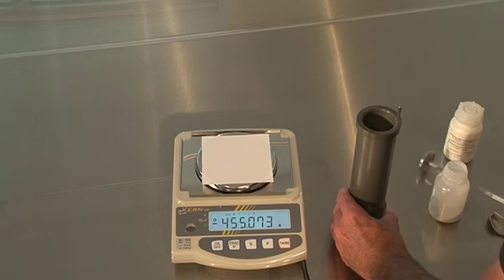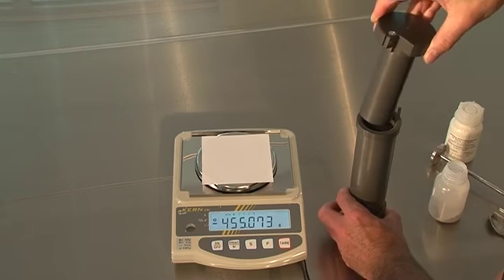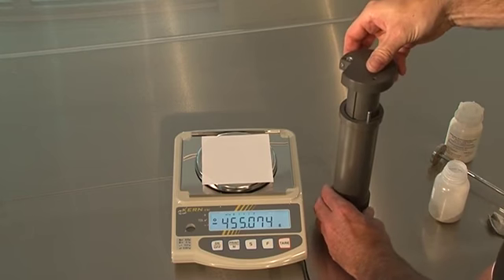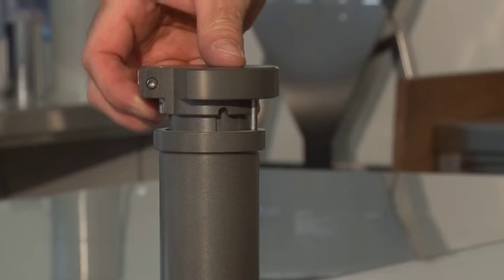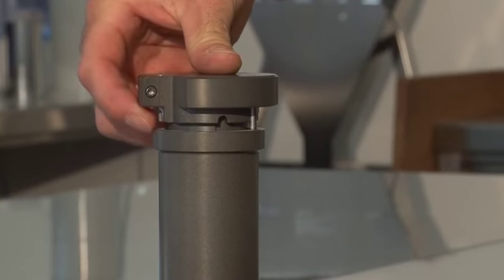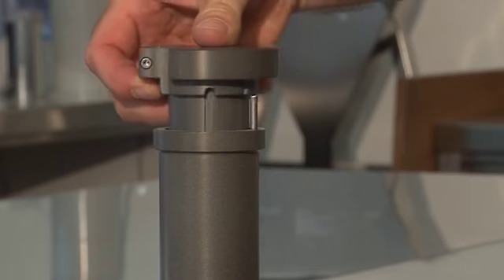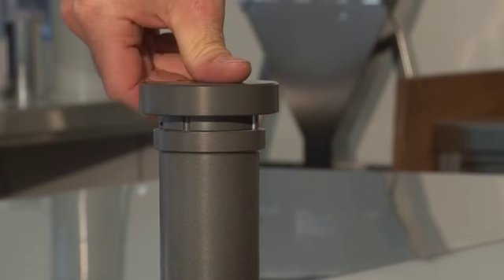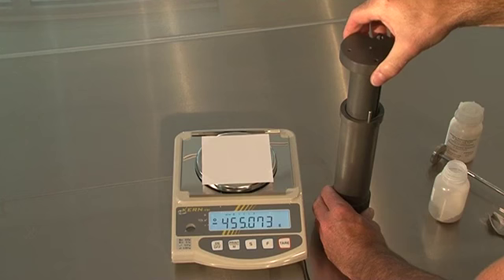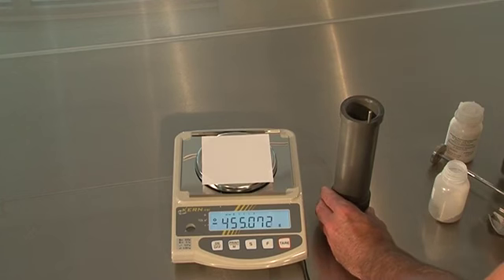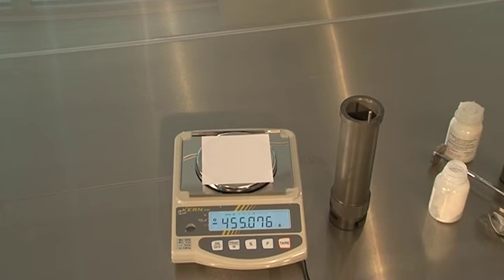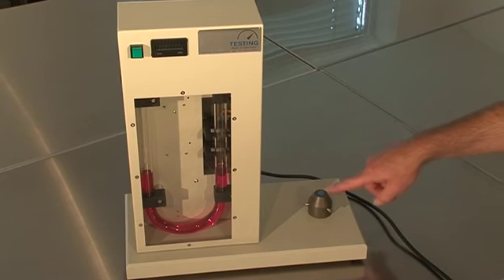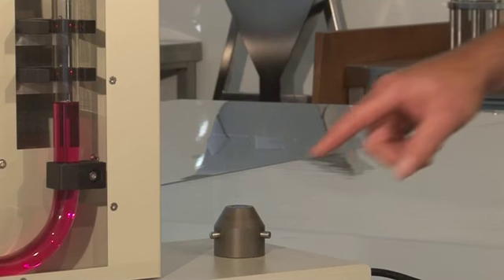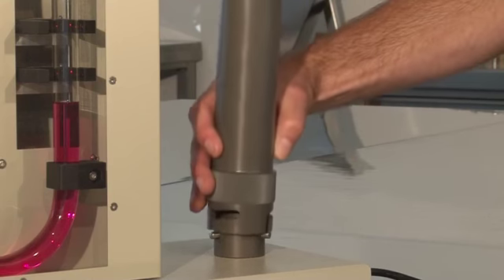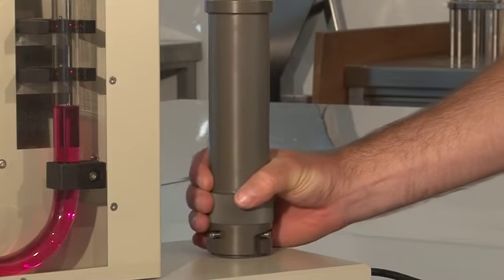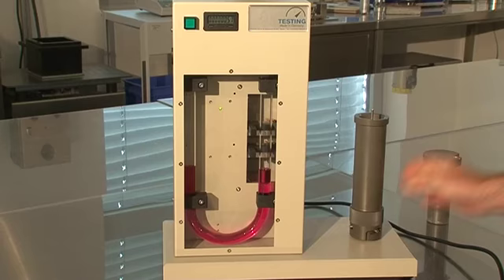Now the reference material is compacted by slowly pressing the plunger so that, without exerting any great pressure, the lower face of the cup is in contact with the upper edge of the measuring cell. The plunger is slowly raised slightly, rotated through 90 degrees and pressed on the material again. Finally, slowly withdraw the plunger without disturbing the powder bed. The suction tube to which the measuring cell is attached must be fitted with a dust filter. The measuring cell is placed on the connection support and fitted on the bayonet lock.